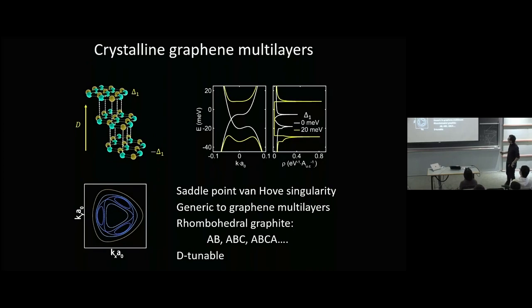And they all share the basic feature that with zero applied electric field, they have usually three Dirac points. Their single particle band structures are described by three Dirac points that touch. And if you zoom out a little bit, it's a parabolic band touching. It's only at very low energies that this happens. But when you apply an electric field, you gap out that parabolic band touching, or cubic band touching, or quartic band touching that you get for higher numbers of layers. And you get some Van Hove singularities either at, or very nearly at, or somewhat nearby the band edge.